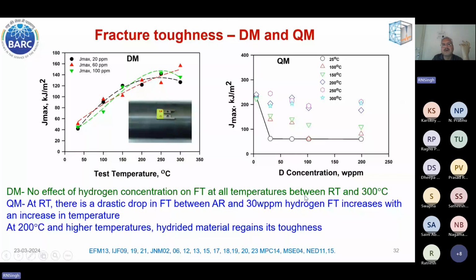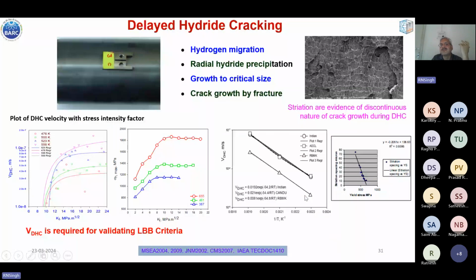This striation spacing with yield strength is shown over here. As the yield strength increases, this striation spacing reduces. That is what this curve shows.